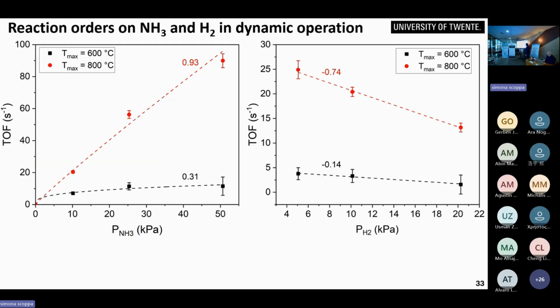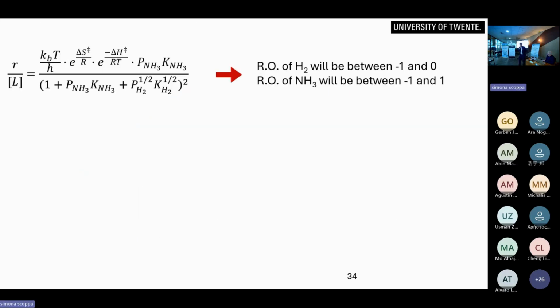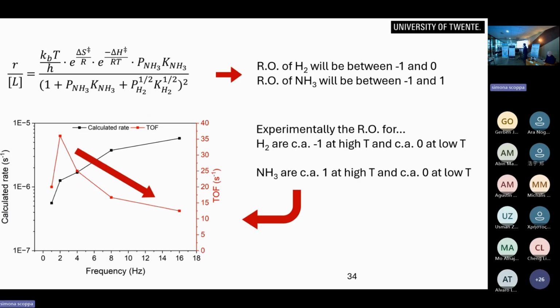But the one that is intriguing is hydrogen, because that gives you the opposite. What you see here is that there is more inhibition when you have the higher temperature. So that suggests that the moment you go to higher temperatures, you're sort of trying to get rid of the hydrogen that is on the surface, and that helps you to accelerate the reaction kinetics at the higher peaks during this pulsation process. But that would be very counterintuitive otherwise in an isothermal process. So obviously, the conclusion from this is that this maxima is linked to the surface coverage fluctuations during these peak temperature swings, rather than just your Arrhenius effects.